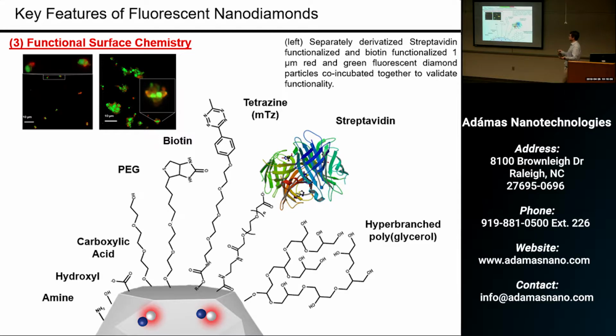mixed them together. And then you see this aggregation, which is really the demonstration of this interaction between biotin and streptavidin over time. So it's a simplistic demonstration, but it is a demonstration that you can functionalize the surface of these particles and not interfere with the functional capability of the molecule, for example, the streptavidin.